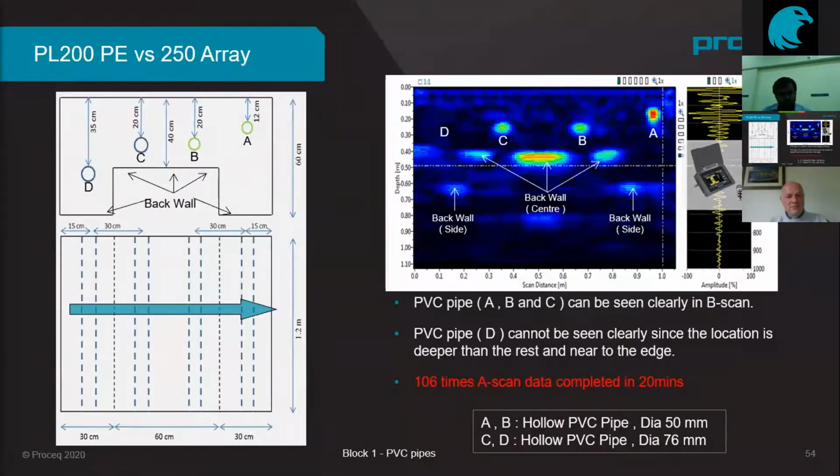In some cases, like Dave mentioned, it's good for total thickness detection, but in a certain range. I'd like to say the maximum you can go is around 50 to 80 cm. It depends on the material density. So in this case, we can have clear information on A, B, C, D, right?